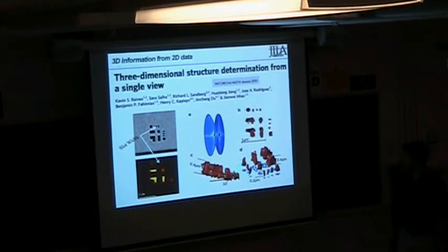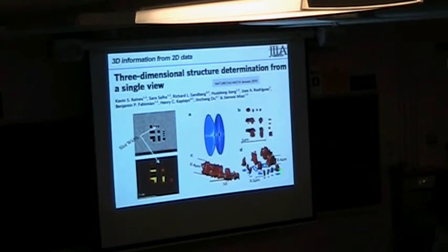So we were able to see, and that was kind of cool, that these smaller slots I was talking about, this is the sample with 50 nanometer slots, appear in our reconstruction to not actually go all the way through the object, and there's no other way that we could tell that was the case.